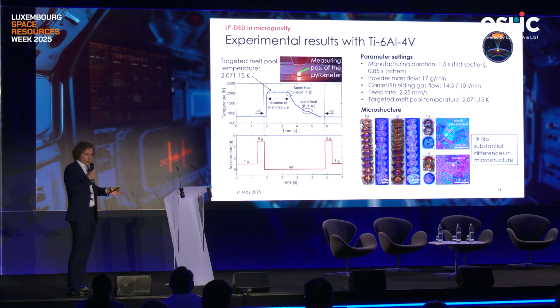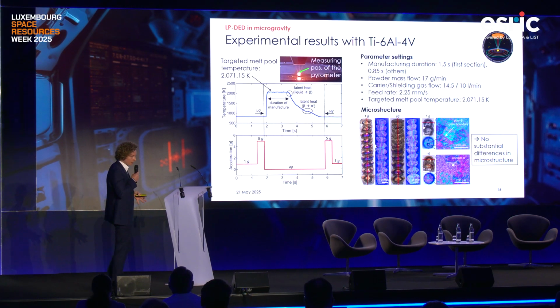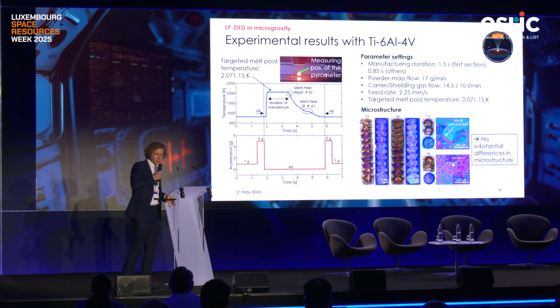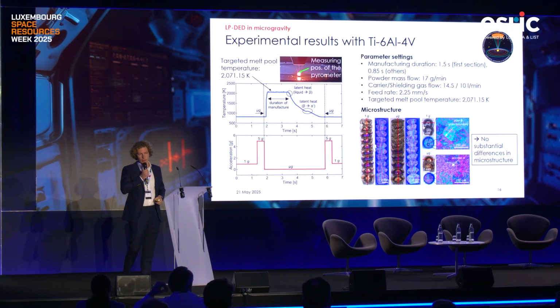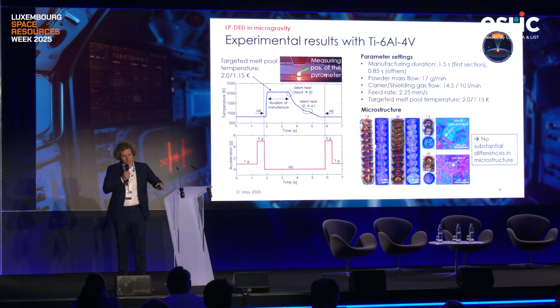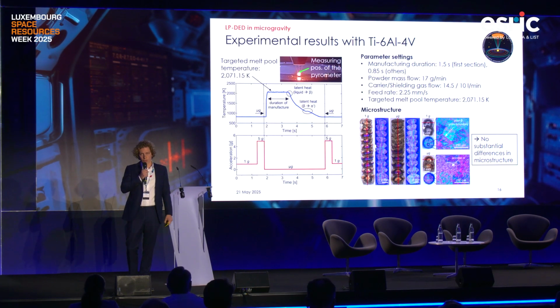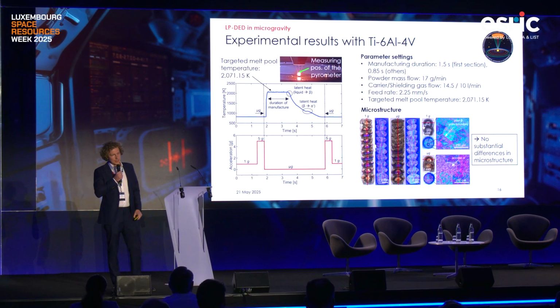Here again on the left side, you can see the manufacturing duration. So we only printed for the first section 1.5 seconds to have enough time for cooling down our melt pool. The temperature is in the blue curve, and the induced acceleration is in the red curve. And there you can see that the temperature drops to the amount that the 5G deceleration of the drop tower facility has no influence anymore.